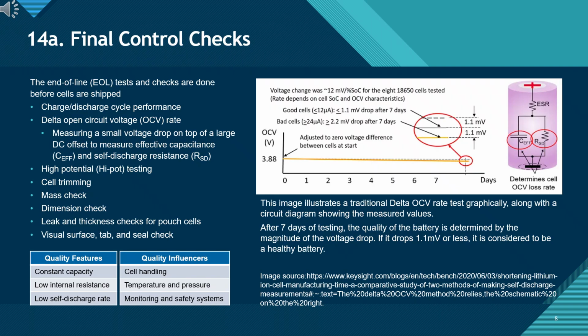One of the most important evaluations is the delta OCV rate test, which monitors the small voltage drop over several days. This drop reflects 2 intrinsic properties of the cell, the effective capacitance, and the self-discharge resistance. Cells that show a voltage drop of 1.1 mV or less after 7 days are considered healthy, while larger drops indicate elevated self-discharge or internal defects.